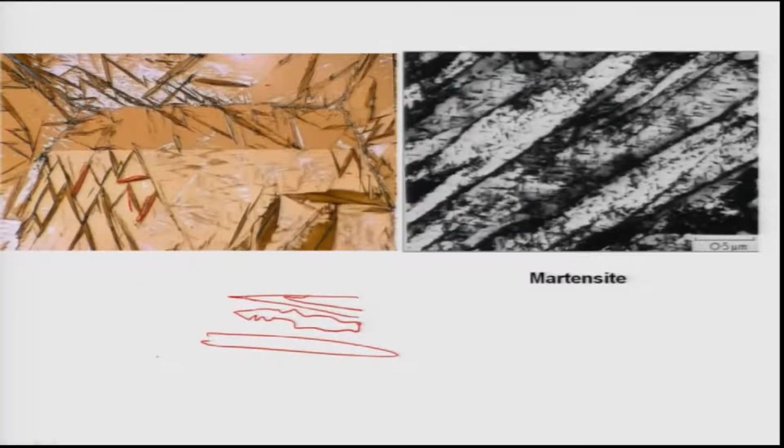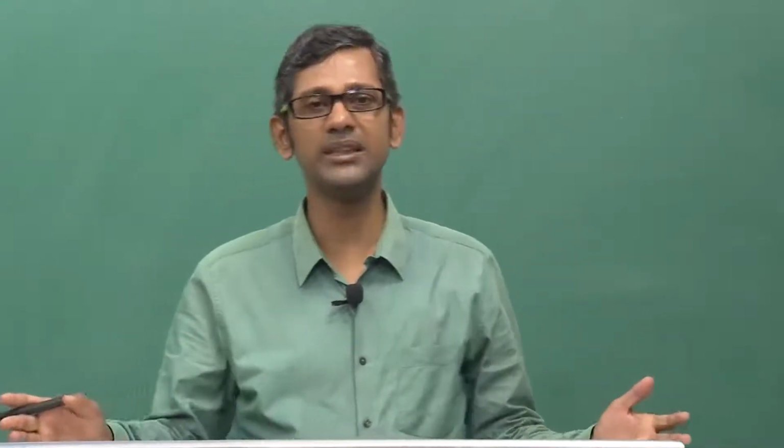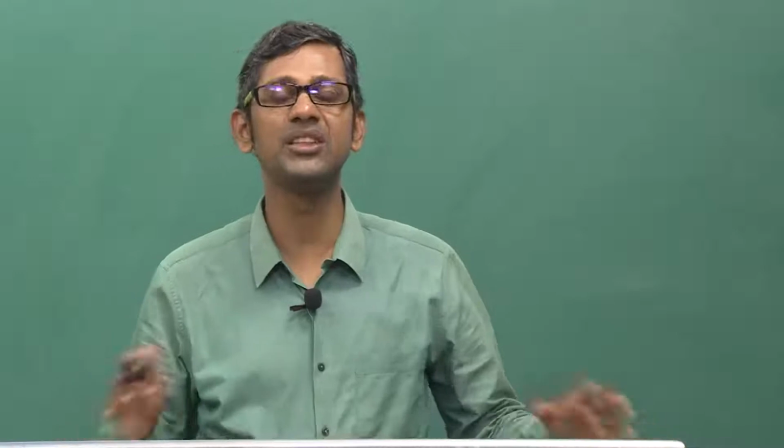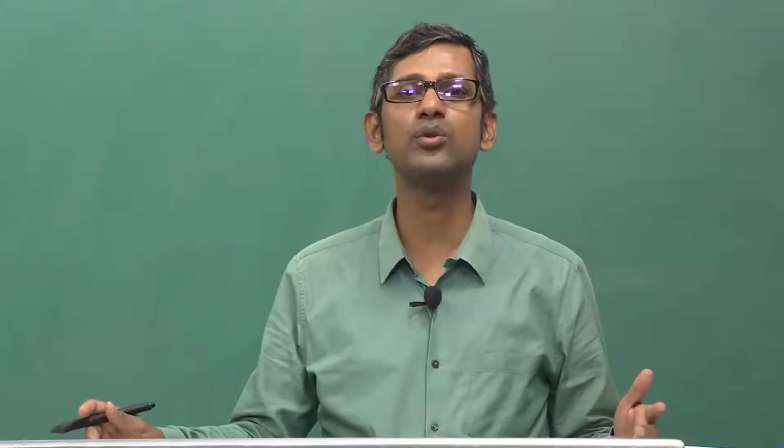Therefore, martensite forms by what is known as a diffusionless transformation, in which none of the species, either carbon or iron or whatever is present in the steel, undergoes any diffusion. They move cooperatively, basically by shear, because it is quenched in water or something else. There is no time for the atoms to diffuse, because diffusion requires time, as you know. So, we have no choice other than a transformation which is dictated by the application of shear forces.